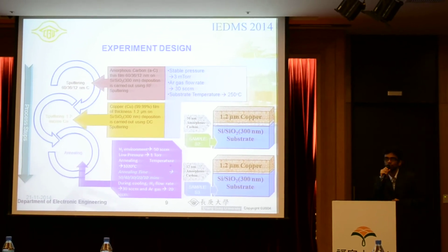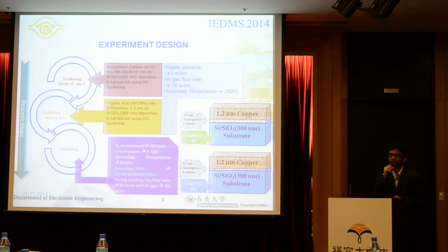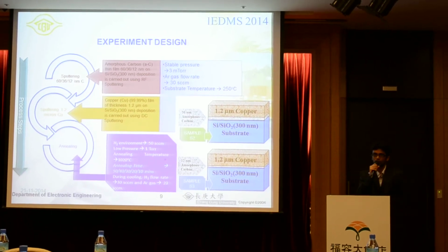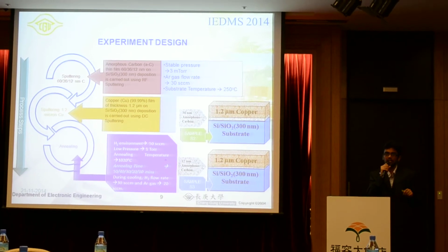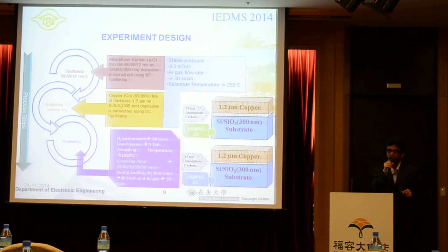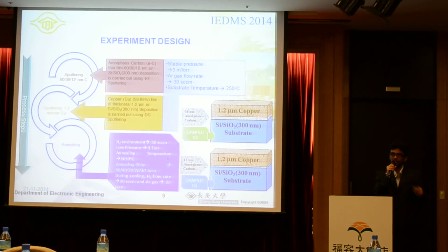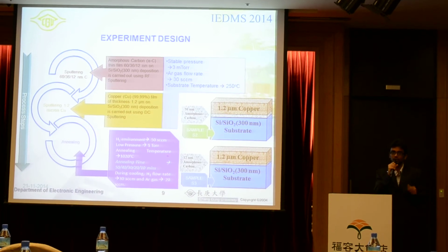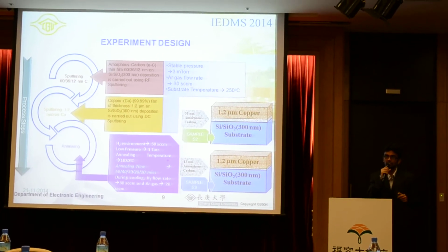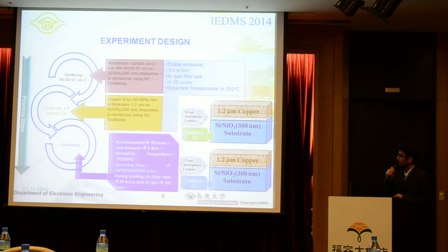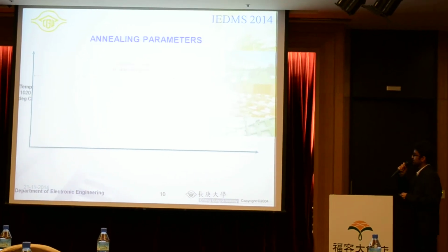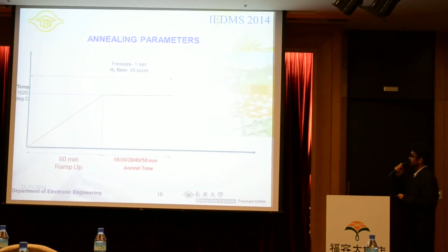Now this is a very important point, because already reported data say that with copper this method is not possible. They have said so, but they haven't taken annealing for more than 5 minutes. But we took annealing for about 10 to 50 minutes and we observed at different points of time, and we could see a mechanism coming up. So again, the annealing is exactly the same, the only difference is the anneal time.